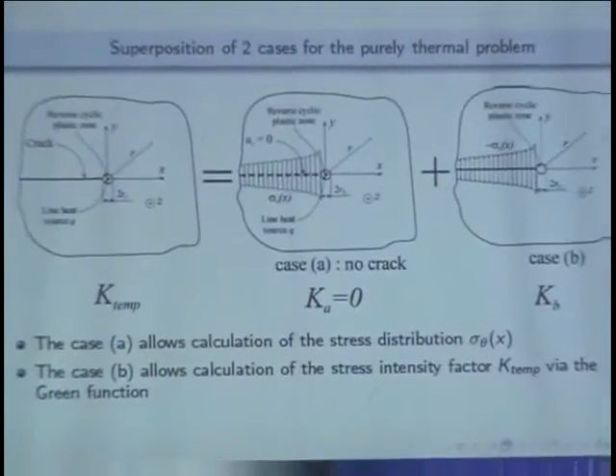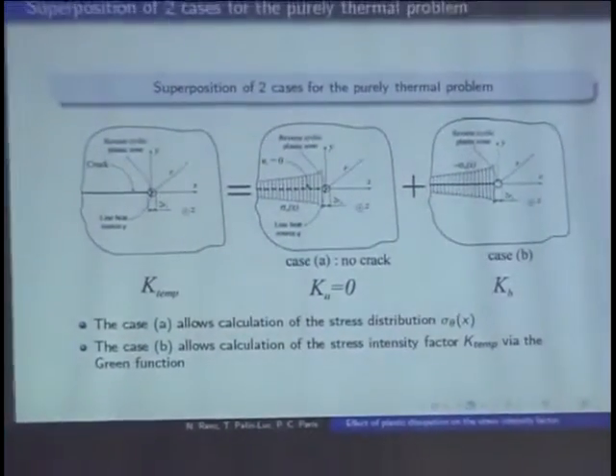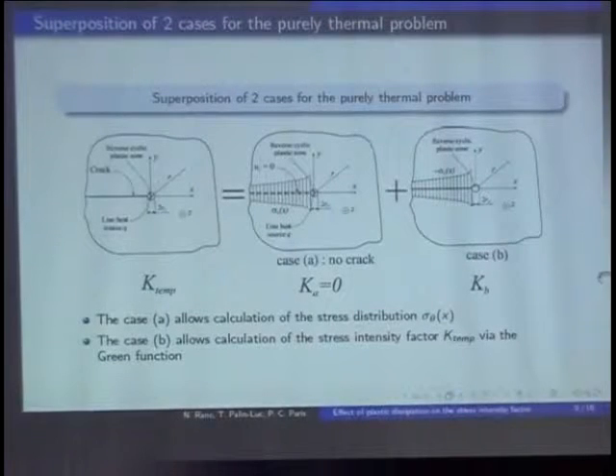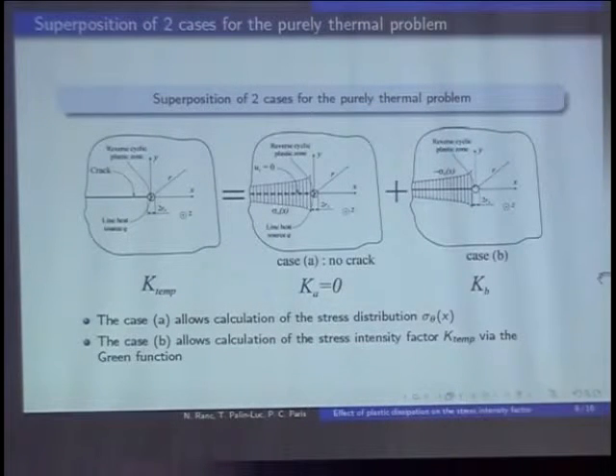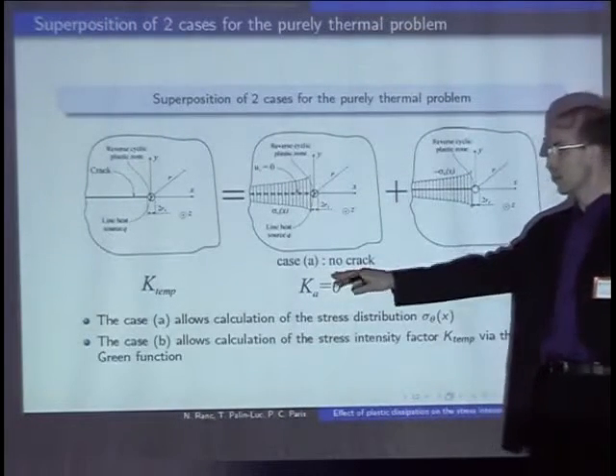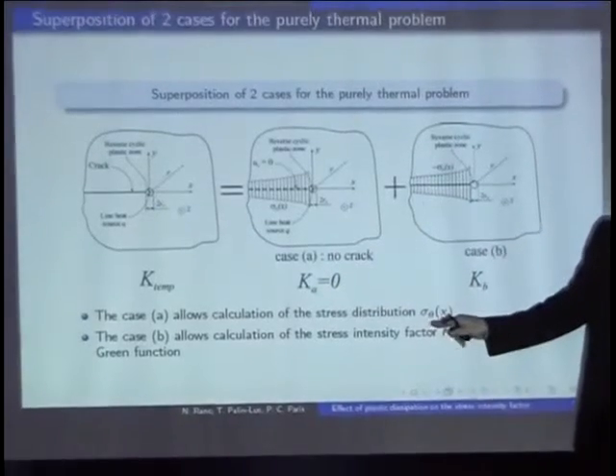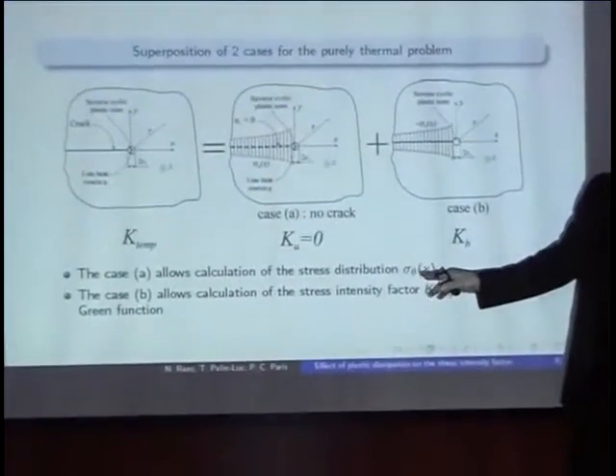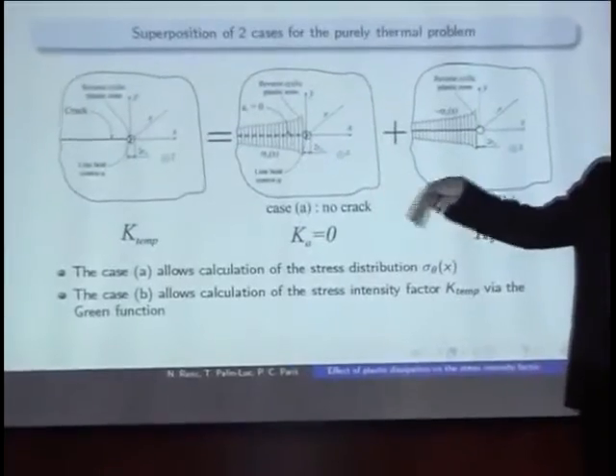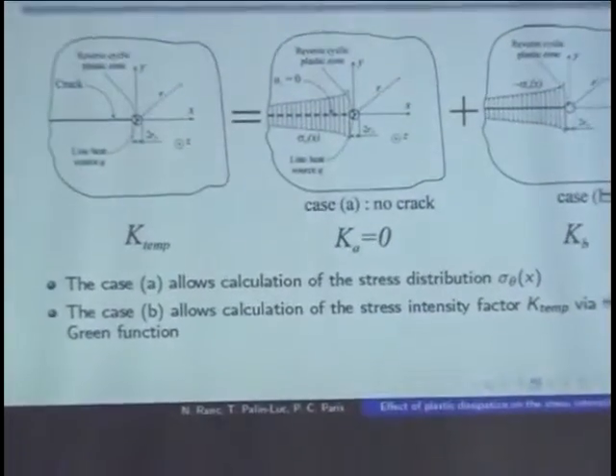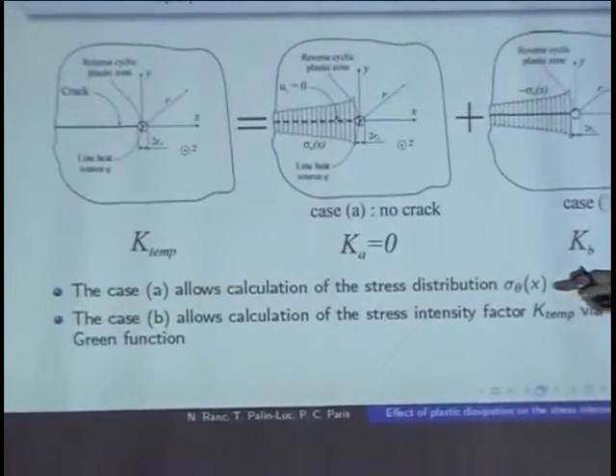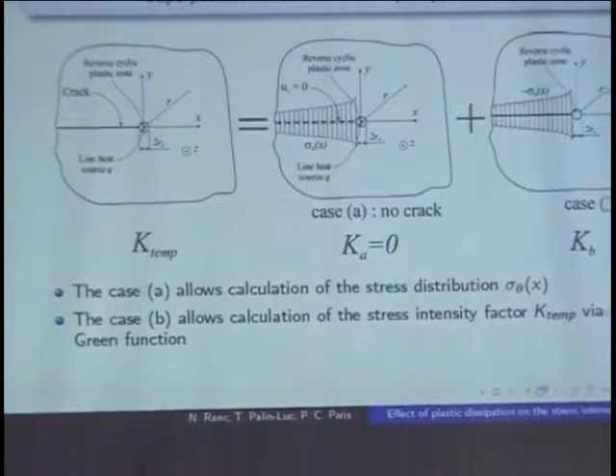Now, if we want to solve the mechanical problem due to temperature, so I mean to compute the effect of this temperature field on the stress, we have separated the problem in two cases. The first case, where there is the distribution of the stress due to temperature with no crack, and then with the Green function, we will compute with this stress field due to temperature what is the effect on the stress intensity factor in the other case.